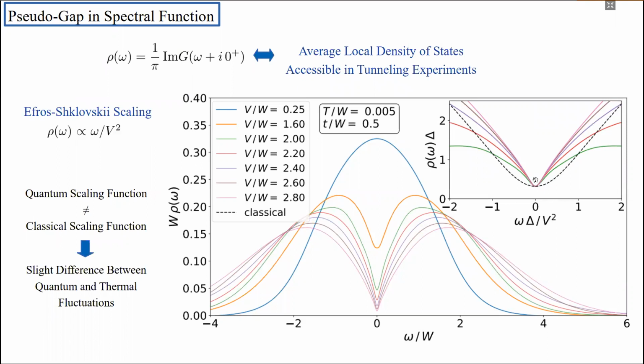What you see with this dashed line here is the classical scaling function. So that's just the scaling function one gets if one sets this hopping t to 0. And what you can see is the quantum scaling function and the thermal, the classical scaling functions are really similar. They have the same slope, 1 over V squared. However, these two scaling functions are not exactly the same, pointing to a slight difference between the roles of quantum and thermal fluctuations.